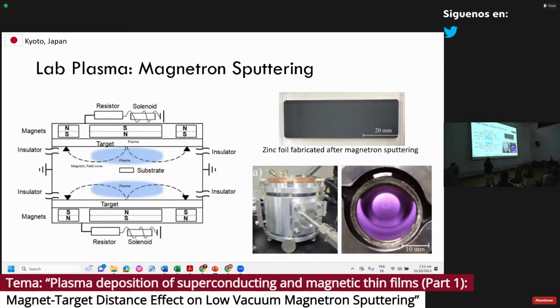And this one is another sputtering device. It's quite small. It's the size of a hamburger. This was developed in Japan as part of my PhD, and we were able to deposit zinc oxide, a transparent conducting oxide, using this machine. And if the parameters are wrong, then instead of depositing something transparent, we will have a zinc foil, which looks exactly like this. Sometimes, if we input too much power, we would destroy the zinc and create a hole on top of the zinc material.